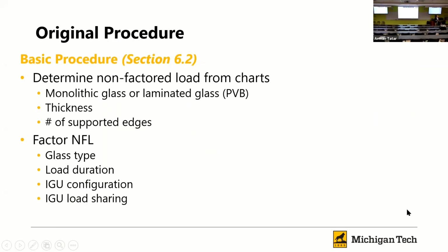Up until 2016, the original procedure was that we used a series of charts. I'll show you one of those in a little bit. They were based on the different standard thicknesses that plate glass comes in, and also the number of supports. Basically we'd get a non-factored load from that, and then go through a series of steps to modify that non-factored load for glass type, so whether it was heat strengthened or fully tempered, and for a longer load duration than, say, a wind load typically is. Also we had an IGU configuration, with different thicknesses of glass in our IGU and the load sharing for those different thicknesses. All of those pieces were in there for factoring.